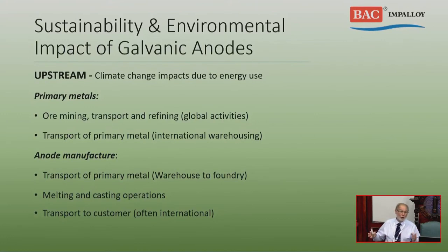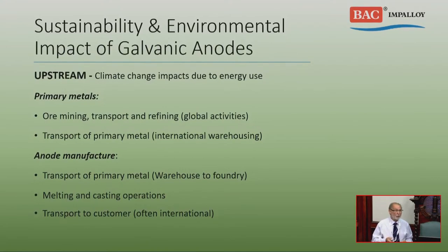So there's a huge hole and a huge discrepancy with these EPDs, if you can find one in the first place. Some of the smelters will in fact tell you what their CO2 equivalent is in terms of tons per ton of metal. But they vary widely. The Emirates, for example, is something like 8 tons per ton of metal. If you go to the French producers, it's down around 2. So that's got to be a recognition or a result of the different power sources that they both use.